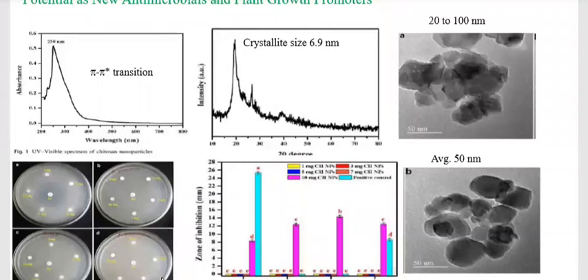The XRD analysis shows well crystalline peaks. The 2θ is of carbon based materials. The crystalline size calculated by the Scherrer formula is 6.9 nanometers. It shows 20 to 100 nanometers, with an average size of 50 nanometers. Antibacterial activity was evaluated at 1, 3, 5, 10 mg concentrations. Only 5 and 10 showed activity; the 10 milligram concentration showed antibacterial activity compared to the positive control kanamycin.